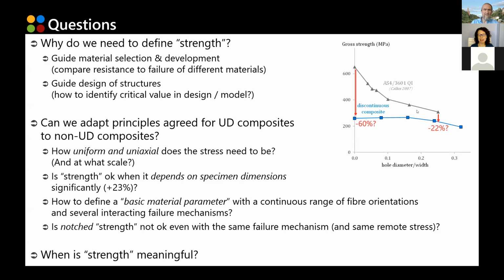How can we define a basic material parameter, which is something that Michael and Federico's document highlighted that we should identify, when we have a continuous range of fiber orientations and when we have several interacting failure mechanisms, so we don't have a separation of failure mechanisms anymore? And is notched strength not okay, even when a notched specimen might have exactly the same failure mechanism as an unnotched one, and even the same remote stress? And finally, when is the definition of strength meaningful?